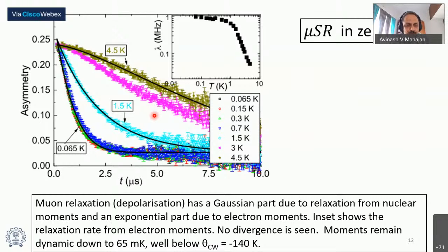Based on the detection of positrons, their angle dependence, and how quickly they relax and so forth, we obtain information about what the local moments are within the chemical system that we are investigating. So the muon is a probe of local moment dynamics within your sample, and it's a very sensitive probe. Also, it's a zero field measurement, so it's really probing the ground state. What is shown here is the muon asymmetry as a function of time, and this is done at various temperatures. The muon is very sensitive to what is happening inside.